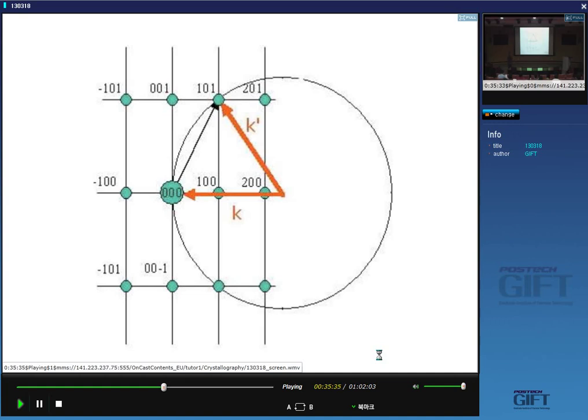So when we put white X-rays onto a material, there's a range of wavelengths, and therefore you will have two spheres, and every point enclosed within that sphere will give you diffraction. So it's obviously easier to get to diffraction conditions when you have white X-rays. Everyone happy with that? Ewald sphere construction?